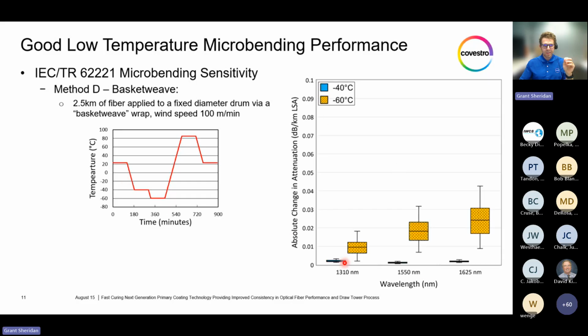As you can see here, I have the microbending performance for this next generation coating at both negative 40 and negative 60 degrees C, and the change of attenuation associated with them. As a sanity check, we can see that the change in attenuation does increase with increasing wavelength, which is an understood and expected phenomenon, as the longer wavelength is more susceptible to microbends and signal loss.